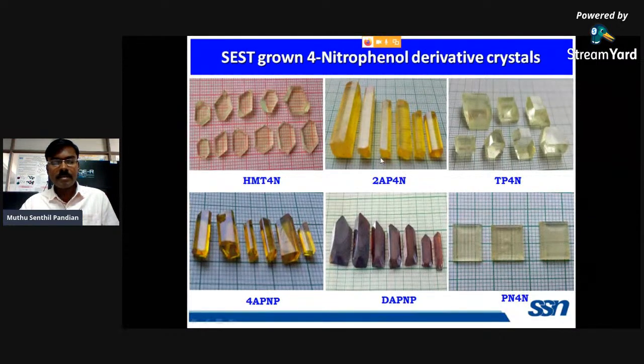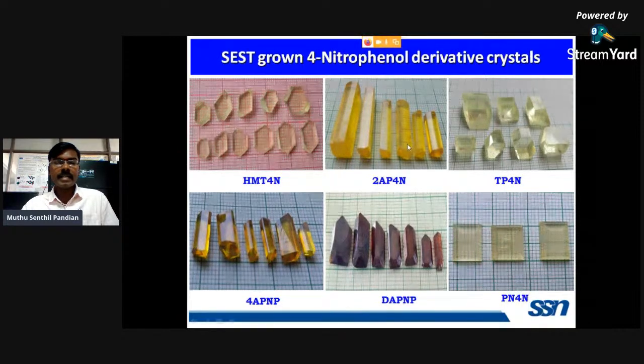So what we have done in the present lecture is we have selected this 2AP4N, 2-amino 4-nitrophenolate single crystal, grown by using the conventional method in beaker and petri dish, and by using the SR method, Sankaranarayanan-Ramasamy method, using this large size glass ampoule, and the rotational Sankaranarayanan-Ramasamy method. We have modified the RSR method. So we have grown this one crystal by these three different techniques, and we have characterized all the grown crystals under identical condition.